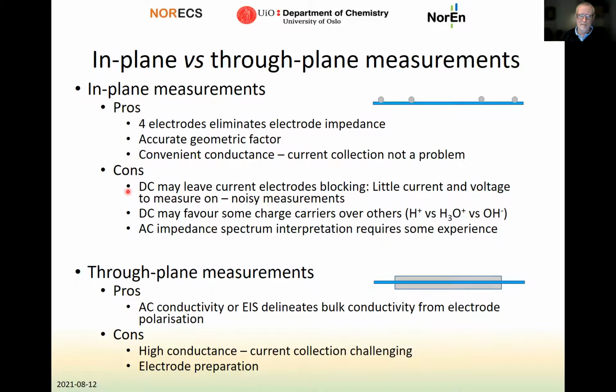On the other hand, if you do DC measurements here, the electrodes may be quite blocking. That means that quite little current goes through, and there is not so much voltage to measure, so you can get quite noisy measurements. Also, DC measurements may favor some carriers over others, because the electrode reaction may be easier for electrons or protons than for, for instance, other ions. So if your membrane is a mixed conductor, you may not get the fully true picture of the total conductivity. And if you make an AC impedance spectrum with an AC machine, the interpretation of that spectrum may take some experience.